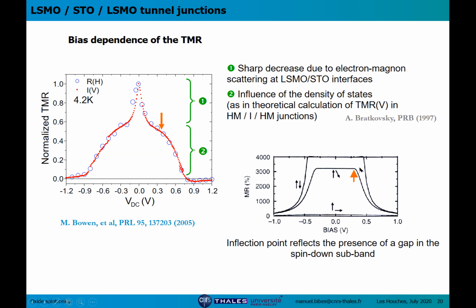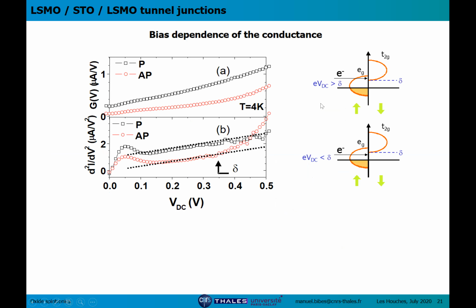But if you decrease a little bit the spin polarization in the calculations, what Bratkovsky found is that indeed you should have a plateau at zero voltage. So he's not considering these electron-magnon processes at all, but then eventually you should get some kind of kink and then a decrease. This kink, this inflection point, reflects the presence of a gap in the spin down subband. Basically, it corresponds to the energy where your electrons are going to be able to reach the spin down band. So let's have a look here on the right at low bias voltage. The electrons can tunnel only into the spin up band. They don't have enough energy to reach the spin down band, whose minimum is separated from the Fermi level by a given energy gap. But when you increase the bias voltage, they may have enough energy to access these states. And then, of course, the effective spin polarization is going to decrease.